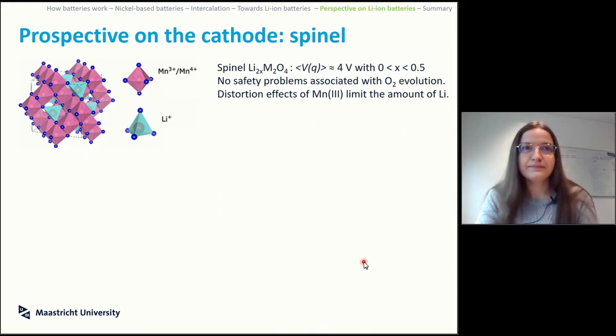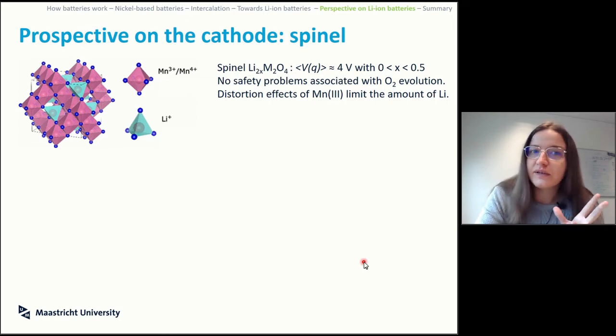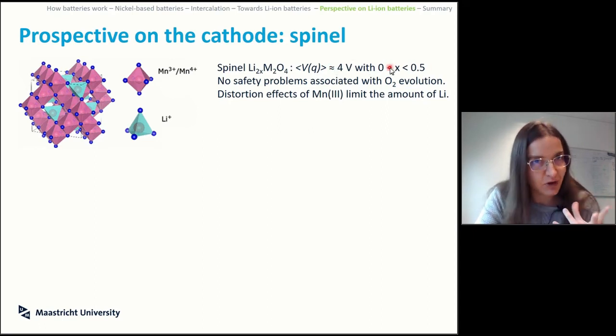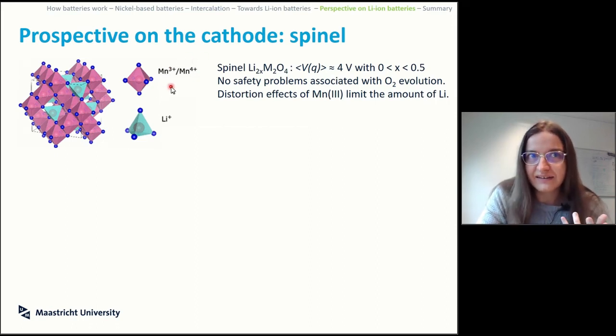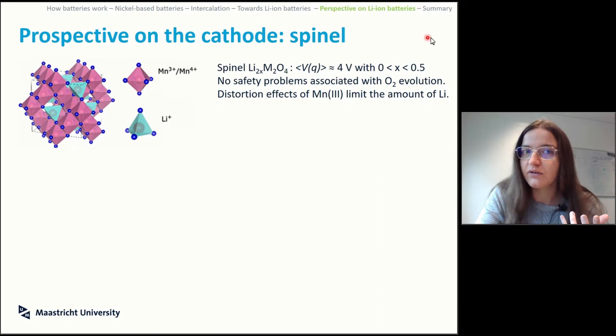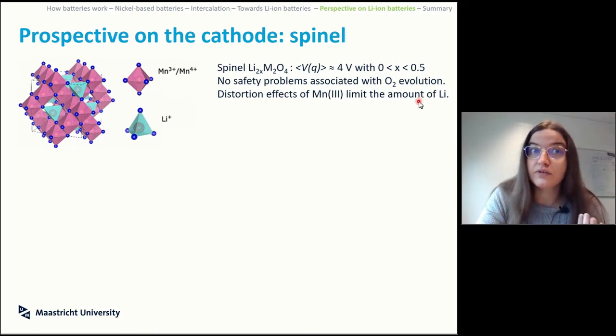So this is a limitation for manganese, but in itself the spinel structure can still be a good idea. So remember, not manganese in this metal, otherwise you have an issue. But when you have the right metal, you are at 4 volt. In some cases, if you are using a Mn3+/Mn4+ Jahn-Teller active redox couple, you need to stay between 0 and 0.5. So you need to limit how much you are charging and discharging your material, because otherwise you know that you distort the structure.